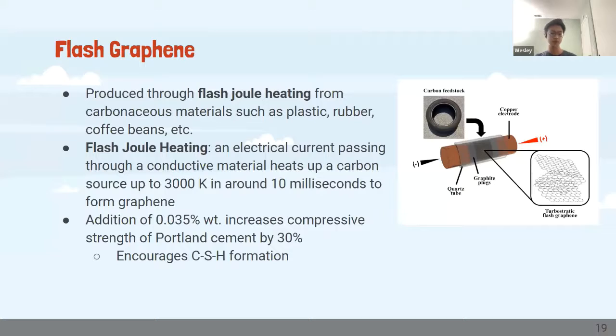But research has shown that adding 0.035 weight percent of flash graphene to Portland cement can increase its compressive strength by about 30%. This is because it encourages CSH formation, which is what Max talks about in one of his previous slides. But yeah, next slide.